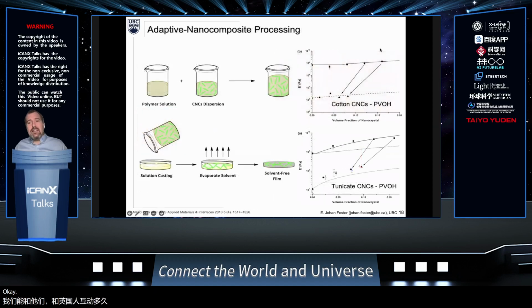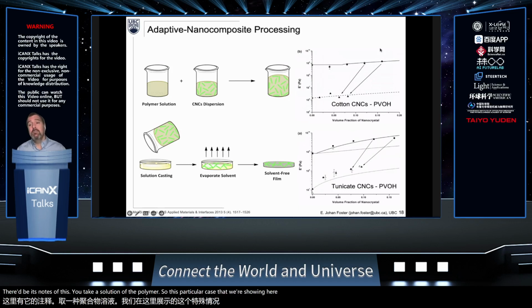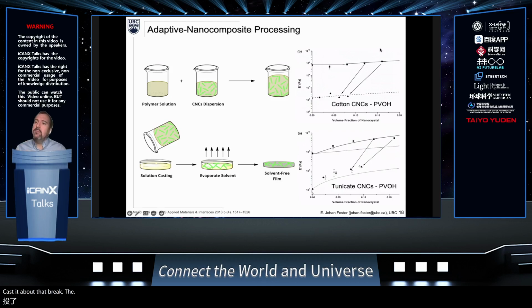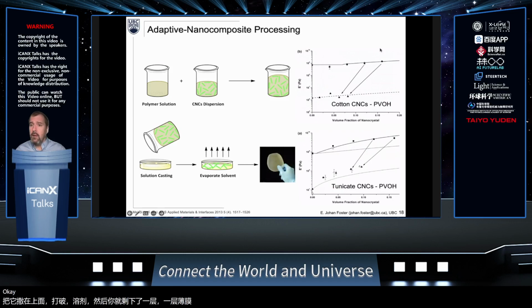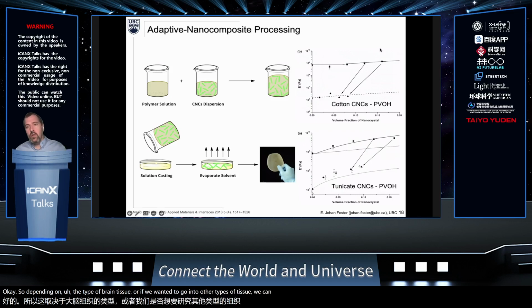Okay. You might ask, how do we actually make the material like this? Well, it's actually pretty straightforward. Once you figure out the ins and outs of this, you take a solution of the polymer. So this particular case that we're showing here is polyvinyl alcohol. So dissolve that in water, disperse cellulose nanocrystals within that, combine them, make sure that they don't flock, or fall out of solution, or start to aggregate. Cast it, evaporate the solvent, and you're left with a film. Okay. Now, depending on the size of the cellulose nanocrystal and the amount of the cellulose nanocrystal we put into this material, we can tune the stiffness in the stiff state and in the soft state. Okay. So depending on the type of brain tissue, or if we wanted to go into other types of tissue, we can tune the mechanical properties of those to be able to exist in different situations.